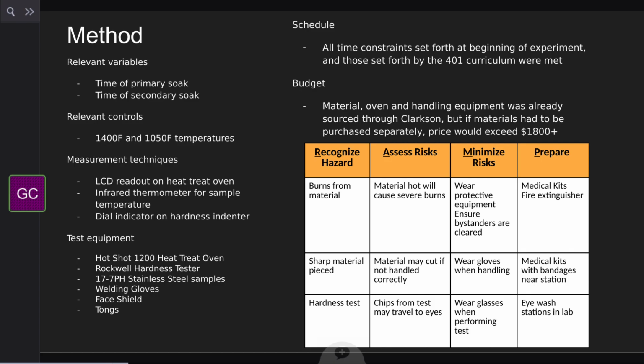For measurement, we used a variety of instruments to gain data for this experiment. The heat treat oven itself has an LCD readout on it, both for live temperature and preset temperature. We used an infrared thermometer to quickly laser the samples to make sure they were safe for handling and to ensure they had cooled down to the temperature we need, roughly 55 degrees. We also used the indenter, which had a dial indicator on it to indicate the hardness the material achieved. In terms of test equipment, the Hotshot 1200 heat treat oven is the oven that we have.